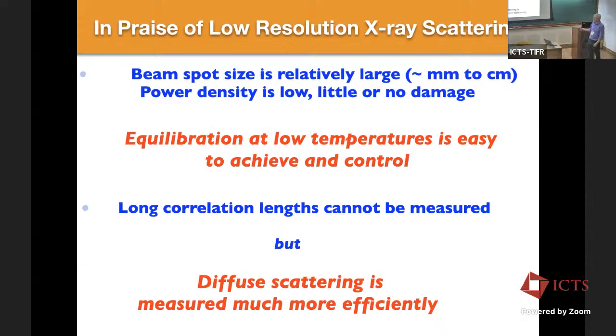It's low resolution, so it means that we cannot measure long correlation lengths. And this is something that the synchrotron or high resolution X-ray diffraction can do. But it means that any features that don't require high resolution, like diffuse scattering, so scattering that is not concentrated into a Bragg peak, we measure that very efficiently, okay? Much more efficiently than the high resolution measurement does.